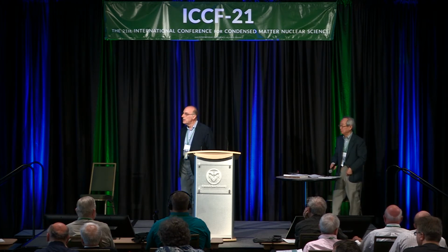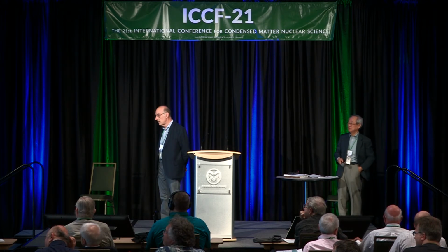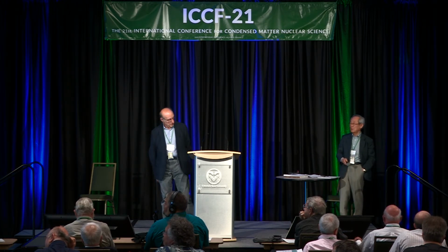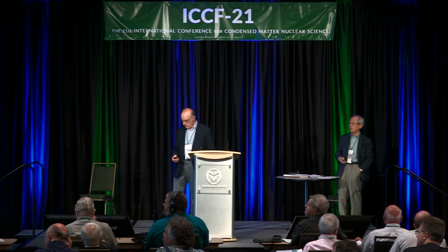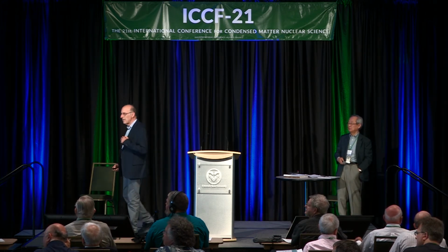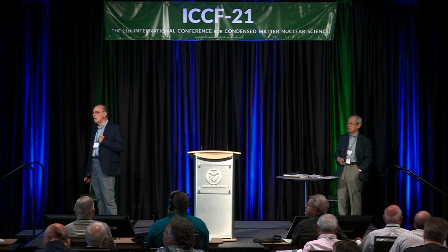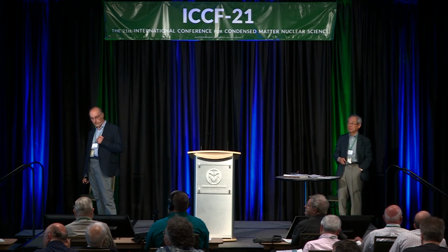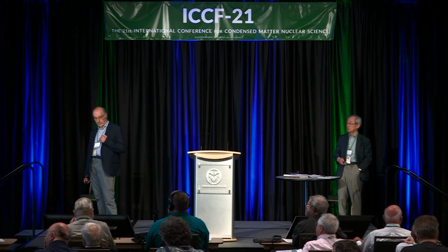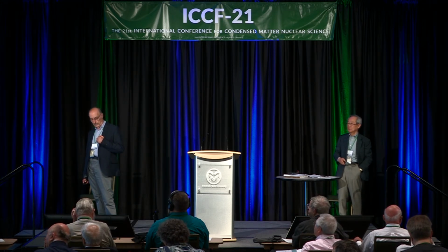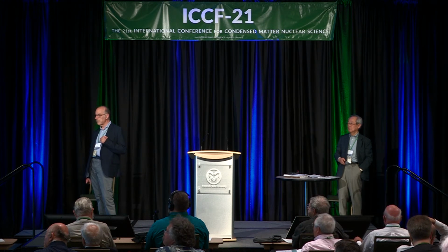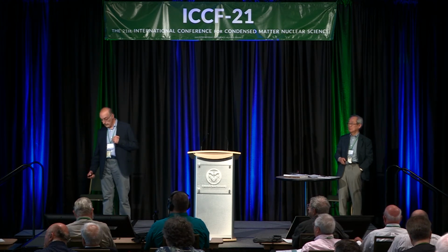In your simulations, when the deuterium comes out or hydrogen comes out, there's a miscibility gap where the chemical potential is flat. And also the diffusion coefficient is down by close to 2 orders of magnitude in the miscibility gap. And so in your simulations, it's conceivable that that would be important to include. I think it would make a difference in your plots.